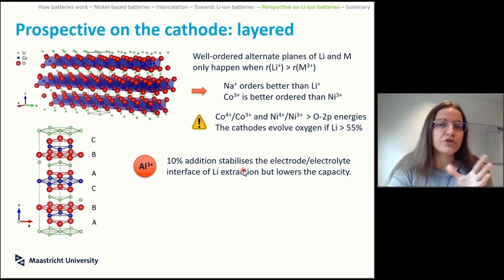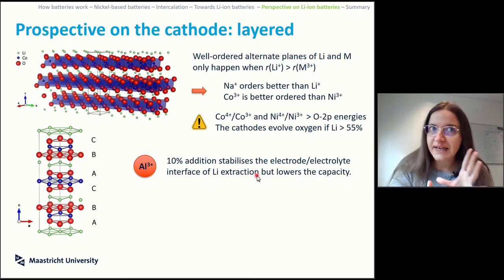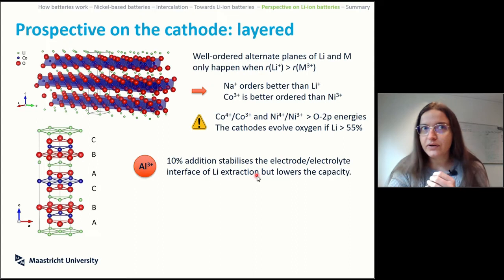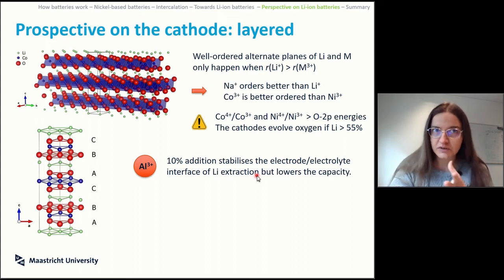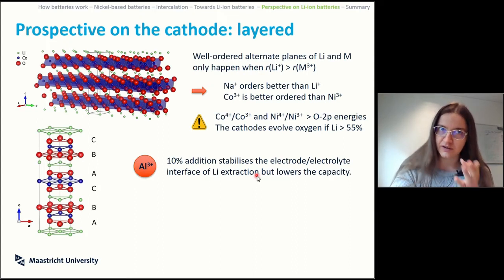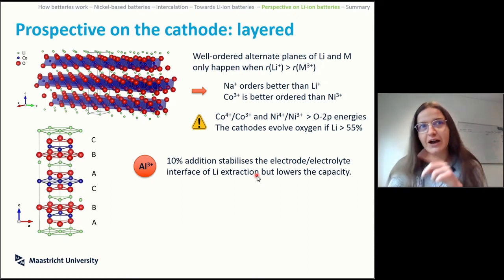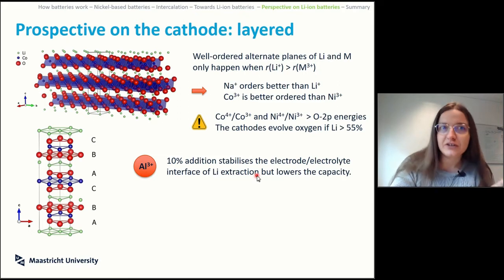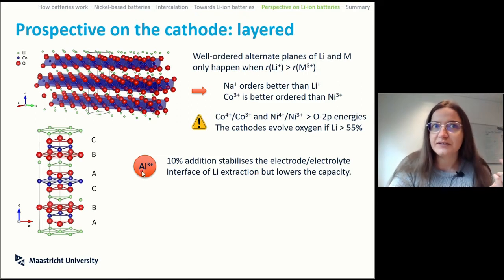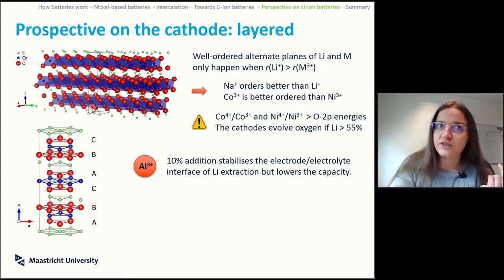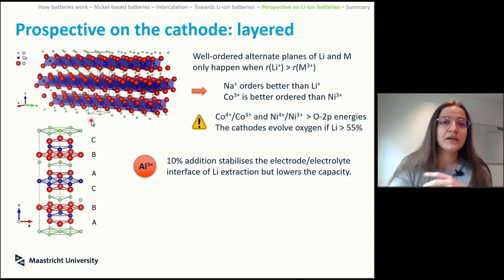With 10% addition, you stabilize this, and the interface gets nicer. But the more stuff you put in that is not involved in the redox couple electrochemistry, the more it inevitably changes how much lithium you can accommodate in the structure. Because aluminum 3 plus cannot have different oxidation states, nothing is compensating the charge of lithium plus entering the structure, so there will be less lithium to accommodate.